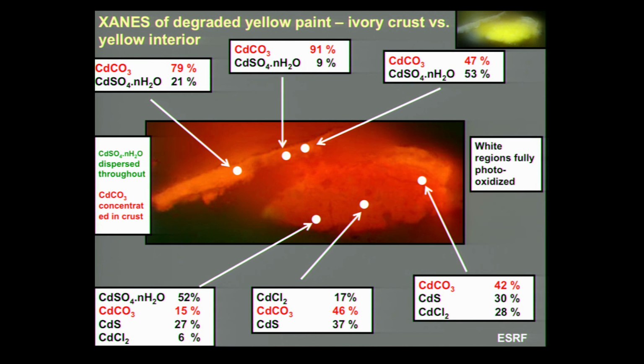And it's more difficult to interpret the cadmium sulfate data because that's actually present throughout the entire paint layer, but we think that's a function of the high solubility of the cadmium sulfate.